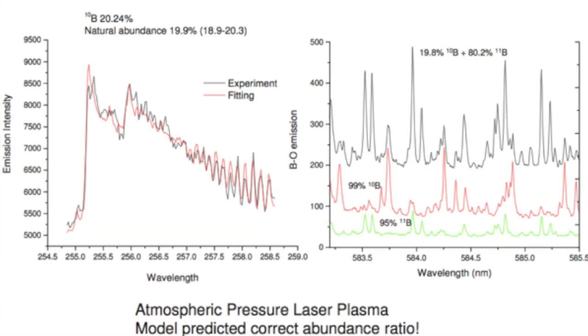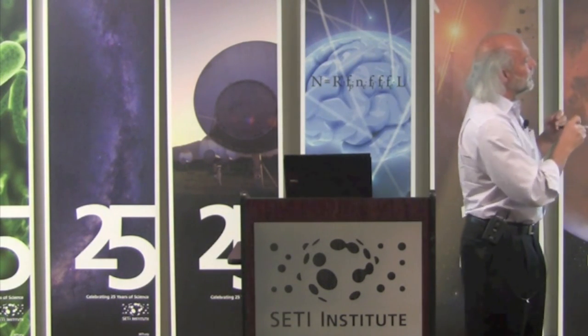And it's kind of cool too, because if you do spread things out, and again, this is very low resolution, you can see regions in the spectrum where one isotope should emit and the other isotope should not. So you can think about how you can make a system with very fine-tuned wavelength filters to only look at one isotope or another and do your isotope ratios that way.